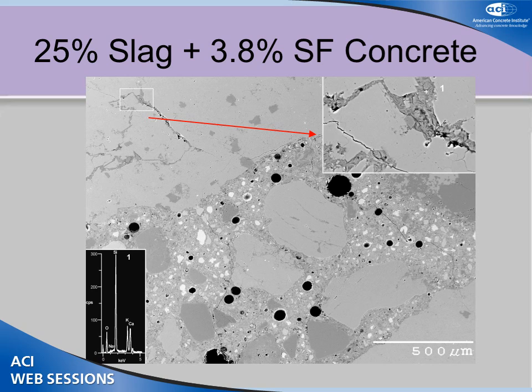In the ternary blend, we're seeing a little bit of gel, but we're not seeing any damage as a result. There's no cracking of the paste. This crack here, we assume, is because it's not connected to anything in the aggregate, that it's formed during sample preparation. And of course, it being a crushed aggregate, there are some fractures in this coarse aggregate.